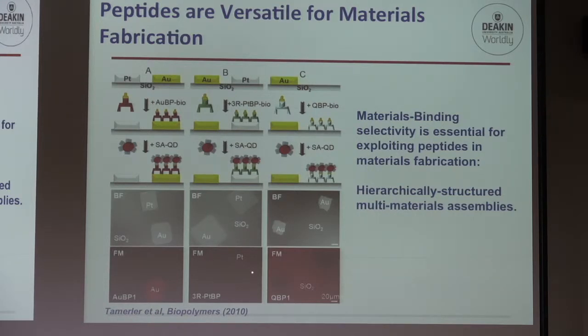In this case, maybe it's not coming out so well, but there really is something sticking here to the platinum pad. I think it's just a bit faint. It's probably the least convincing of them all. And here you've got a difference between gold and silica, and you can see that this quartz binding, or silica binding peptide, is binding to the silica, but not to the gold. So there is definite selectivity there, and you can be using this to make complex 3D arrangements.